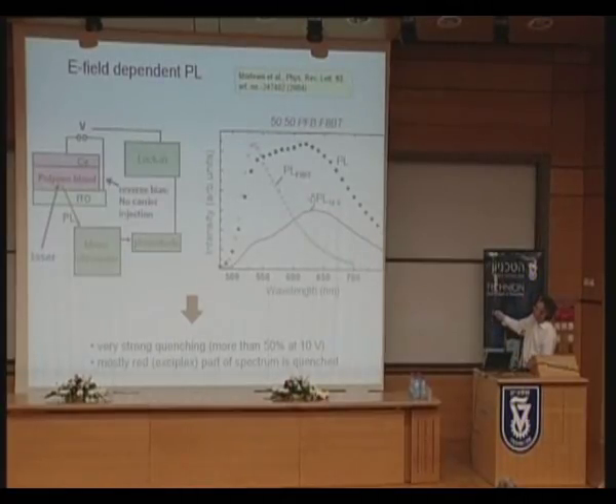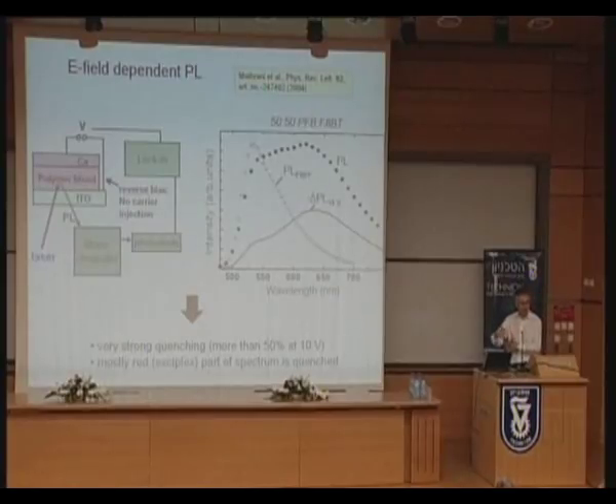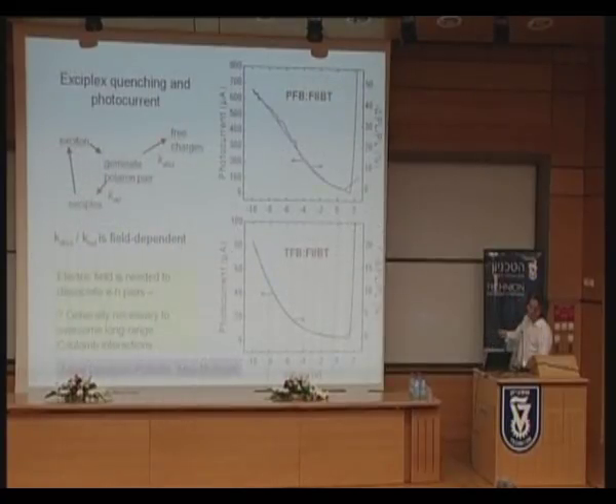And what we see is that the luminescence, the black dots, is the full luminescence signal. The red line is the change in luminescence when the voltage goes on. We've quenched the luminescence by 50%. And that quenching is associated with free charges, electrons and holes, that do escape one another, rather than them being bound at the heterojunction. Now, in fact, it's at a very early stage, where we have a hot excitation at the heterojunction, that the branching between bound and charge separated occurs. It's not once the exciplex has settled.